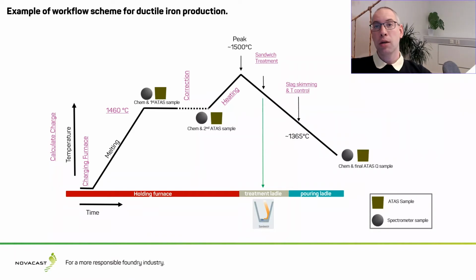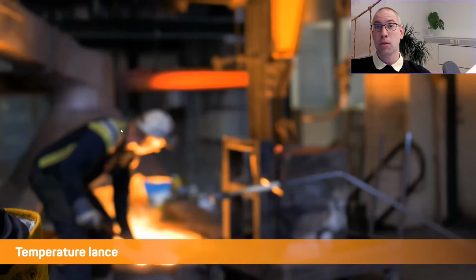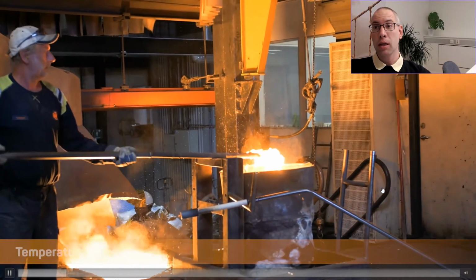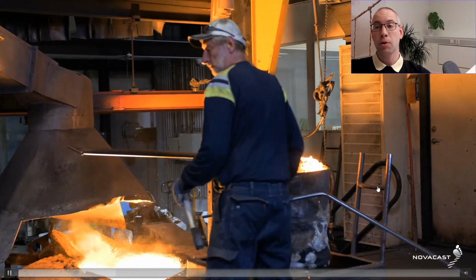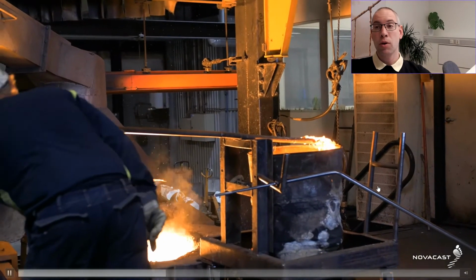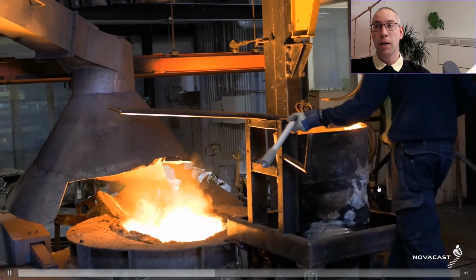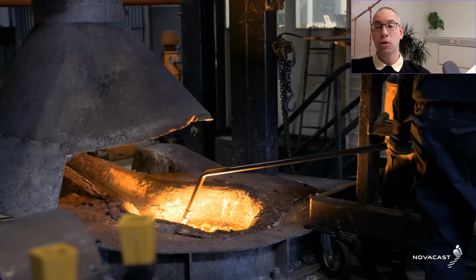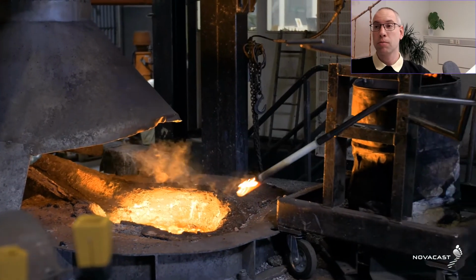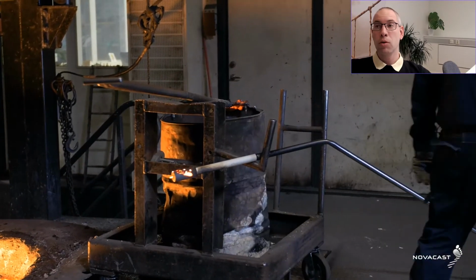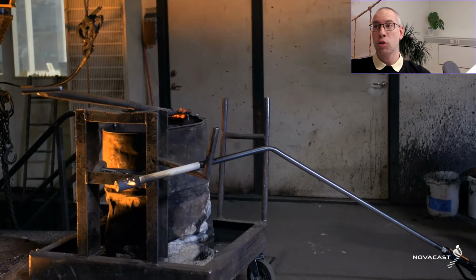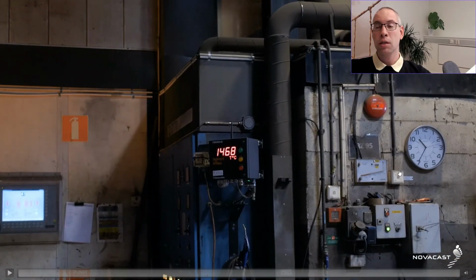So when we do this, then we usually have an idea of what temperature we should aim for after melting the charged materials. In this case, we have set it up to 1460 degrees. So operators are deslagging in order that they are able to take a temperature reading. The temperature reading is one of the key elements in the foundry, especially in the melt shop. So we have to be really careful to measure temperature as many times as possible. So operator has done his job. Now he waits for the temperature reading, and in this case it's 1468 degrees, which is close to what we would like to have. So good job.